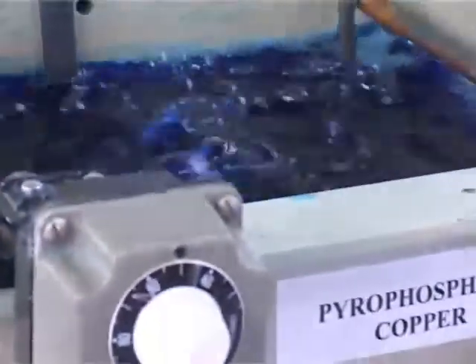Because weight is at such a premium, it is worth doing more processing on the conductor to get a lighter one. An alternative material for stabilising superconductors is high purity aluminium. It's very, very expensive but it's much lighter. One of the difficulties with an aluminium conductor is that it's very difficult to join together. You can try to weld it but the welding process will tend to destroy the superconductor. So what we do is a soldering process. Unfortunately you can't solder directly to high purity aluminium so it has to be copper plated, which is a very nasty and expensive process — but again the fact that the weight is at such a premium means it's still worth doing.